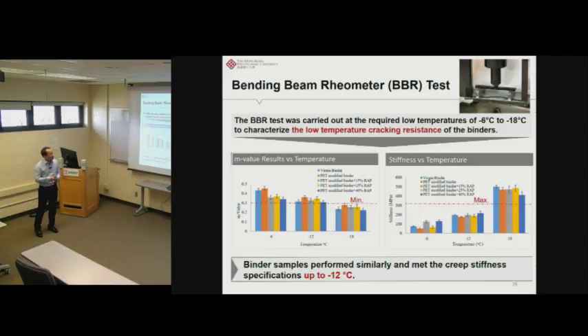So in addition to the DSR test, we also conducted the BBR test. Although in Hong Kong, usually we don't need to run the BBR test because of the very warm climate, as researchers we always need to do a comprehensive study to know how the material behaves at low temperature. For the BBR test, we can get two parameters, the M value and the stiffness. For the M value, we want it to be as large as possible. For the stiffness value, we want it to be smaller, to not be that stiff, to have good low temperature cracking resistance.